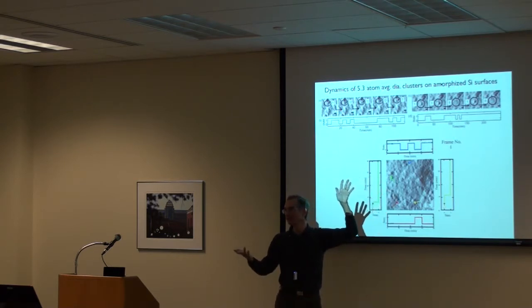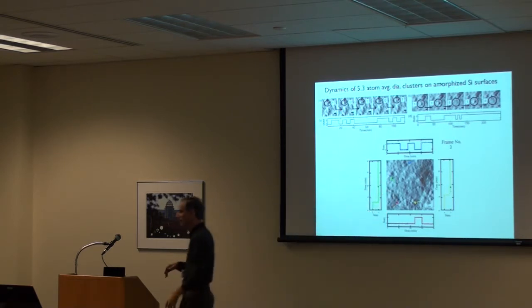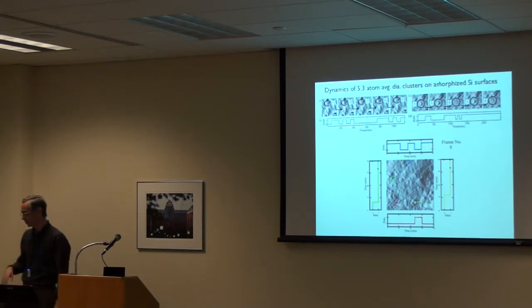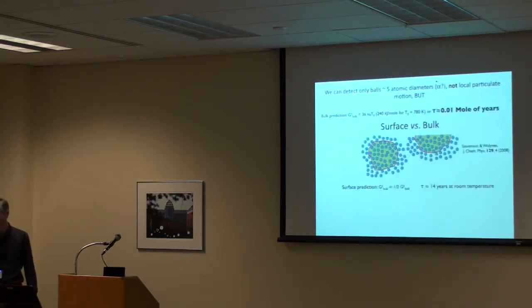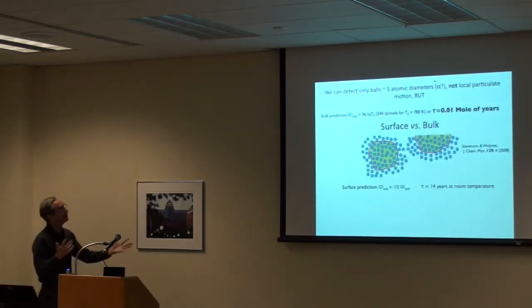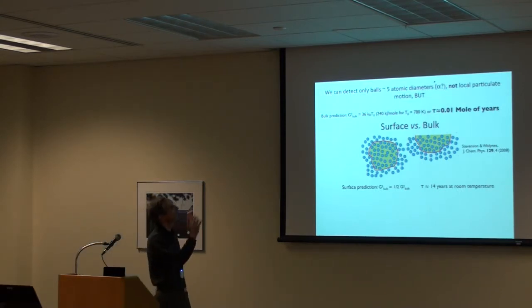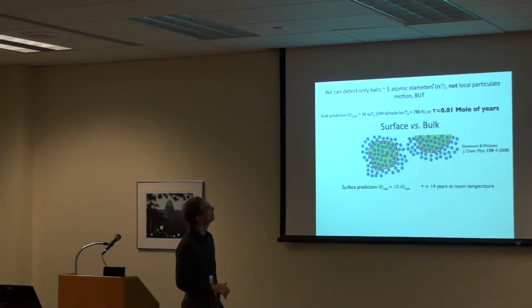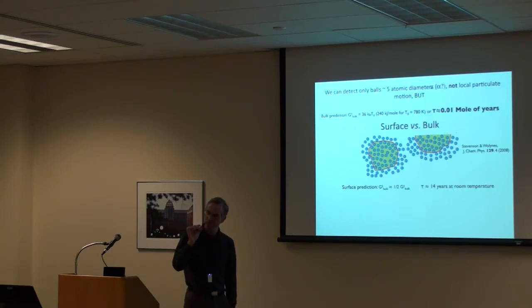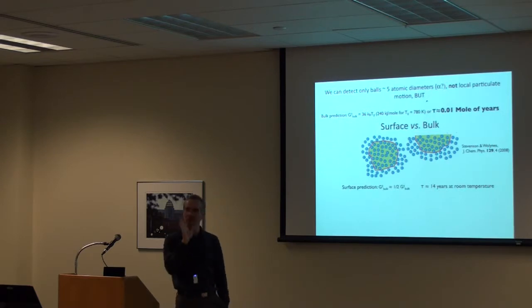The same relative cluster size compared to the size of the atoms, and the same kinds of two-state motions are occurring back and forth on that surface. So we can detect these balls that are a little less than 5 atoms in diameter. We don't have quite good enough resolution yet to actually look at vibrations or motions of individual atoms within these balls, but that's actually something we're working on. I won't let Sweet graduate until he gets that, wherever he is.